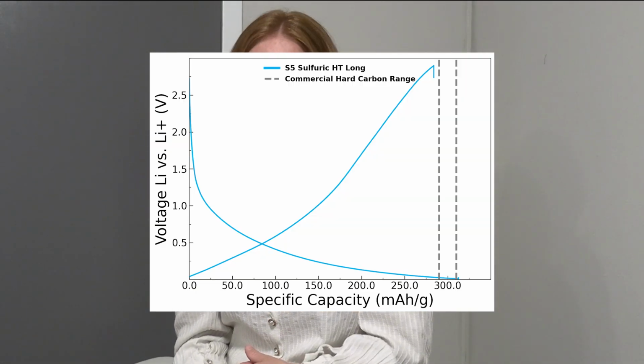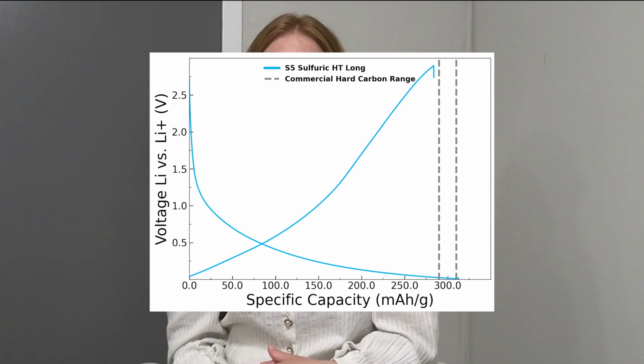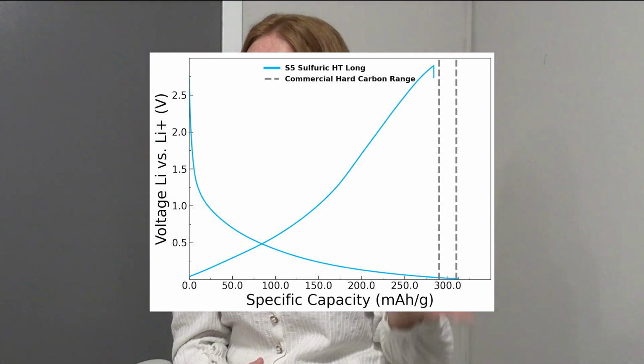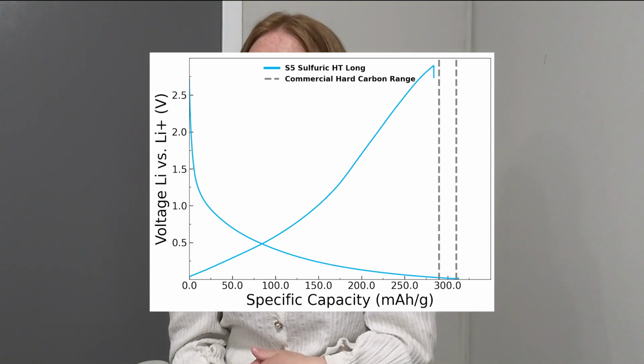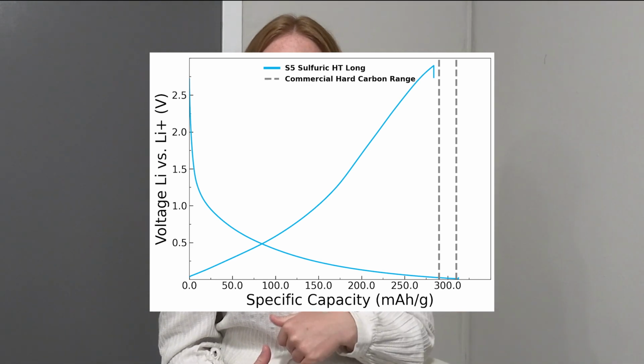This gave us hard carbon that we were able to cycle with both lithium and sodium. And the lithium cell ended up showing a specific capacity of 310 milliamp hours per gram, which ends up being comparable to the commercial hard carbon that's currently being used in industry. So not only were we able to take some tires out of our streets and recycle some of that waste, but we're also able to make batteries that cycle with comparable values to commercial hard carbon, effectively killing 2 birds with 1 stone.